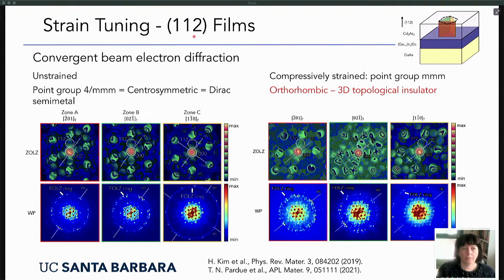Okay, and so what's shown on this slide is 112 oriented films. And the technique we use here is convergent beam electron diffraction. That's a technique that can actually determine point groups. Okay, so these are all experimental convergent beam electron diffraction patterns. On the left, you see the results. This is along different zone axes, so looking along different directions of these sample films.